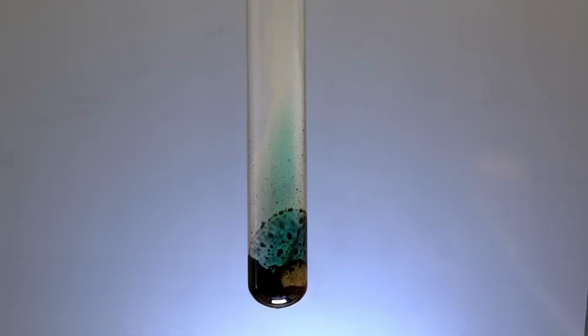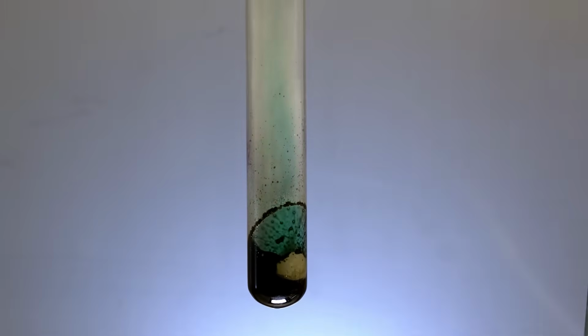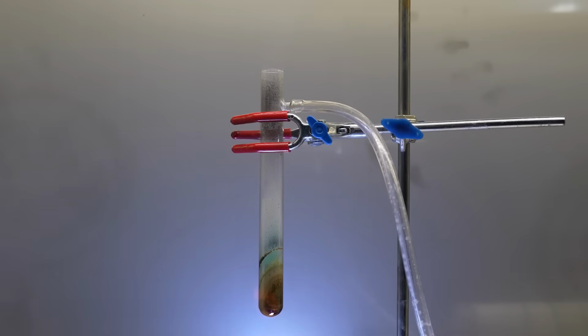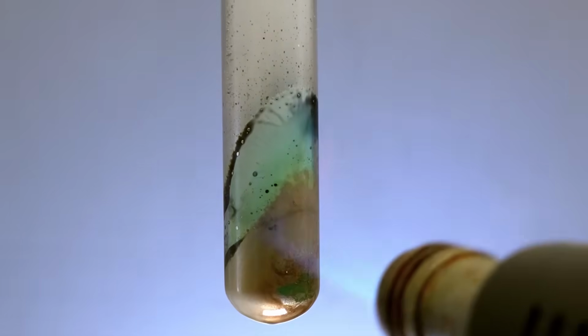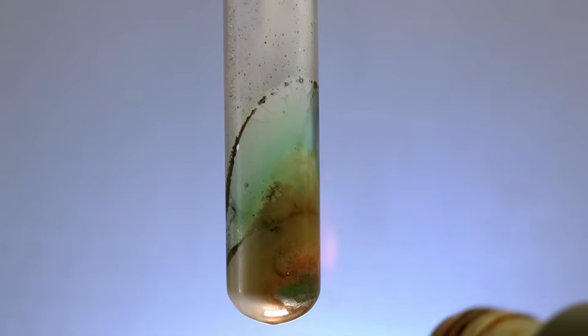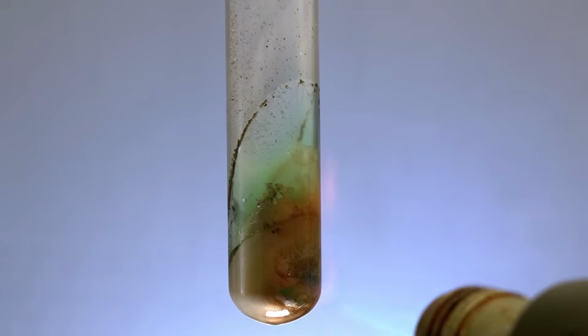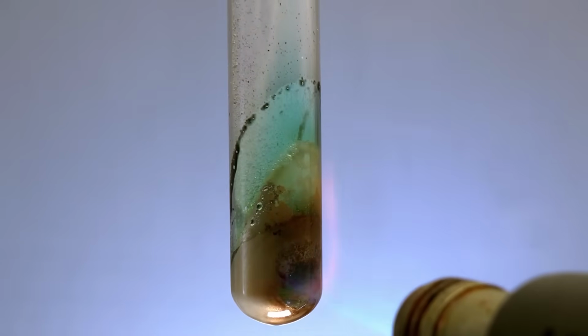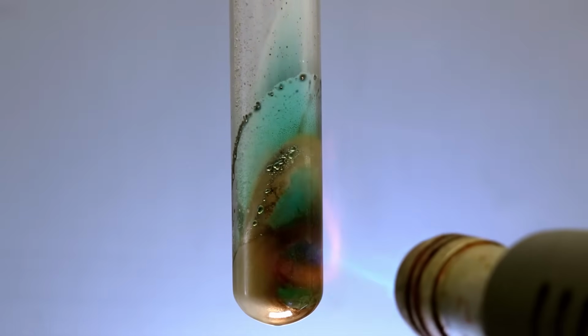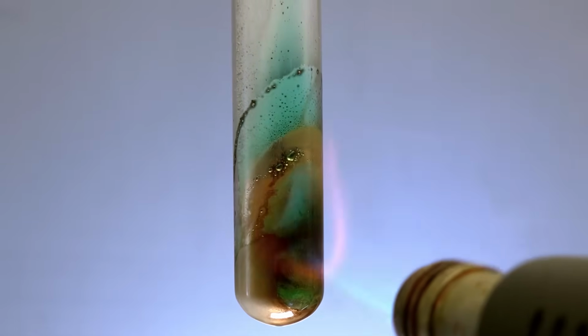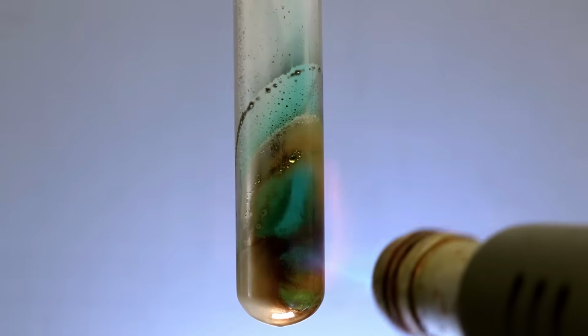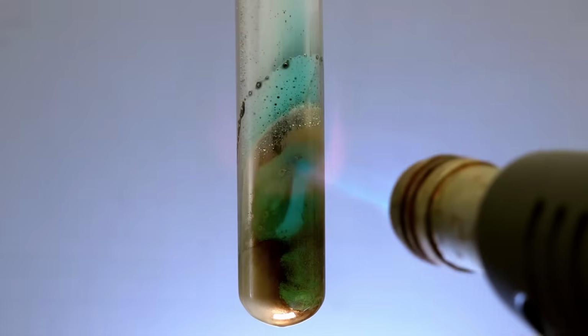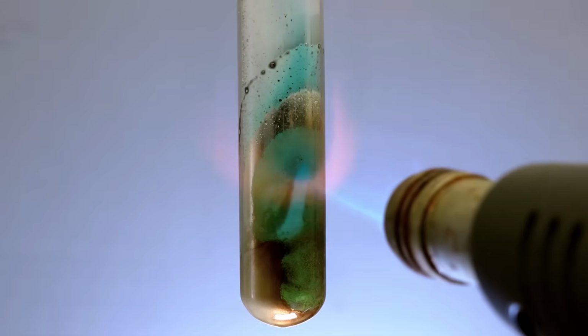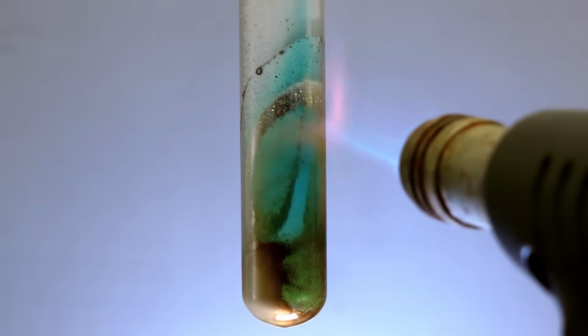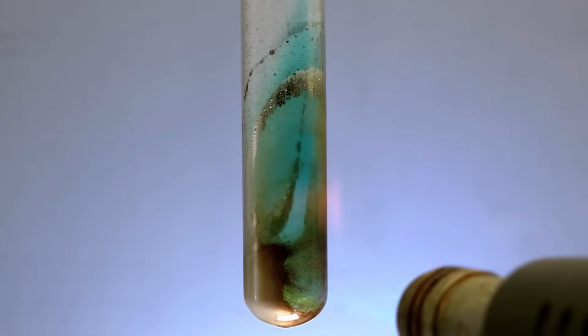The resulting metal vapors were green. Some of the vapors escaped from the test tube and burned with bright violet sparks. To be sure that the potassium vapors are green, I heated the test tube again with the remaining azide and the freshly obtained potassium. Interestingly, in this case the potassium evaporated quite easily and without reacting with the glass, resulting in the test tube filling with beautiful emerald-colored potassium vapors. Well, I finally managed to obtain a gaseous metal at atmospheric pressure and also prevent its oxidation.